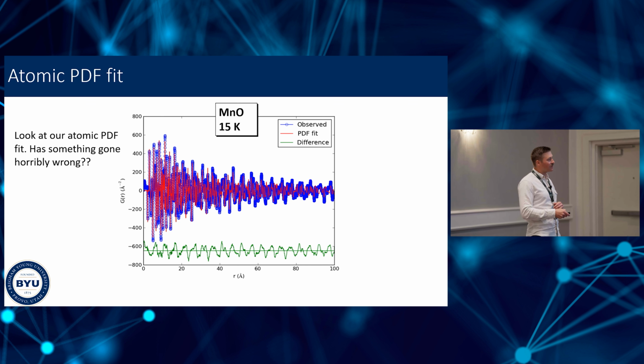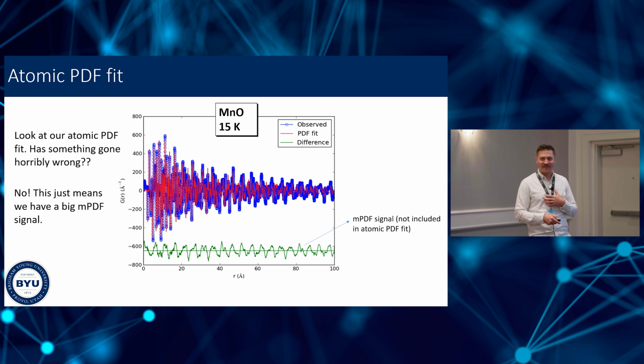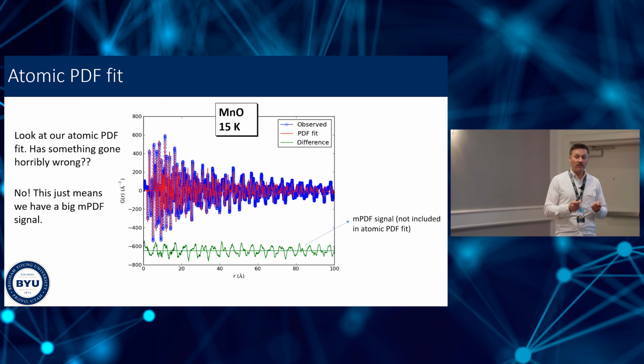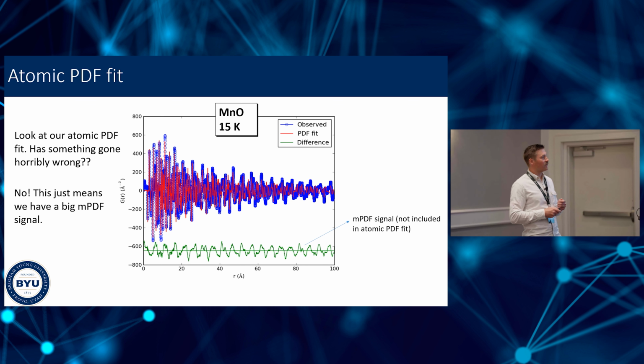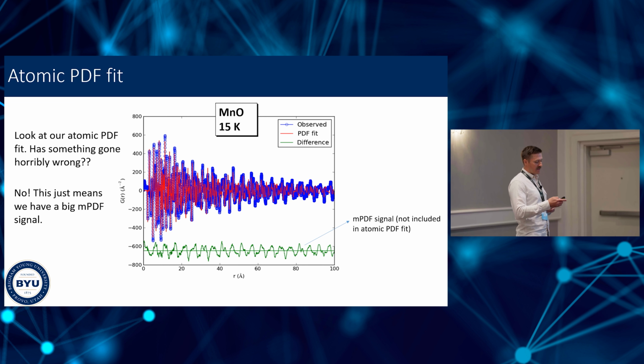However, I was thrilled when I saw this, because this does not mean that our sample was bad or the experiment was bad. This just means we have a gigantic magnetic PDF signal, which is not included in the atomic PDF. So the red line that I'm showing here was produced by just including the nuclear, the atomic correlations in the model. But of course that leaves out the magnetic PDF. So whatever magnetic PDF signal is in there will show up in this fit residual. And this is clearly a very structured fit residual, so there's something in there.